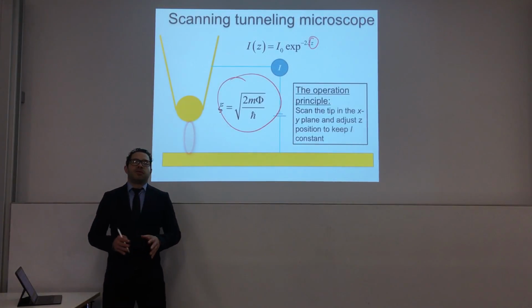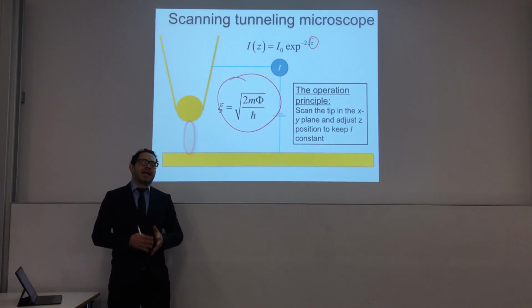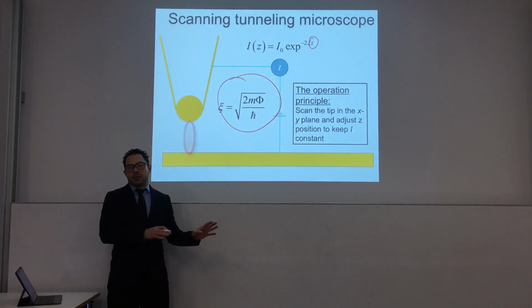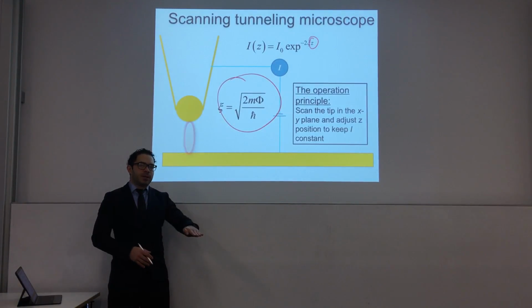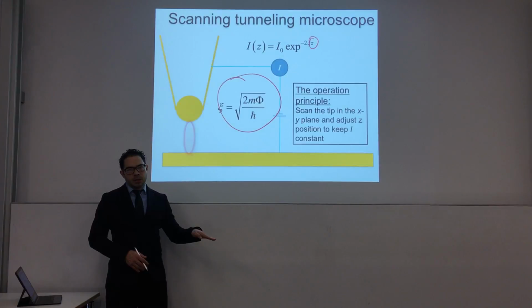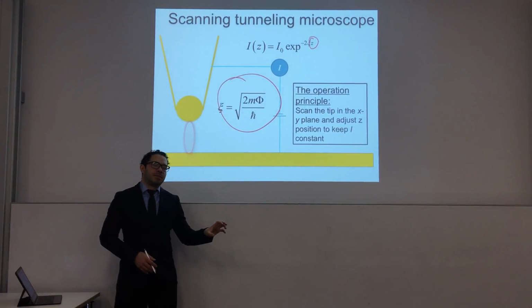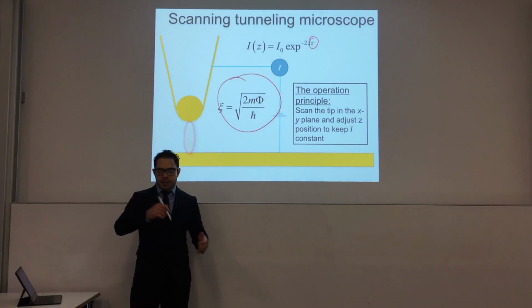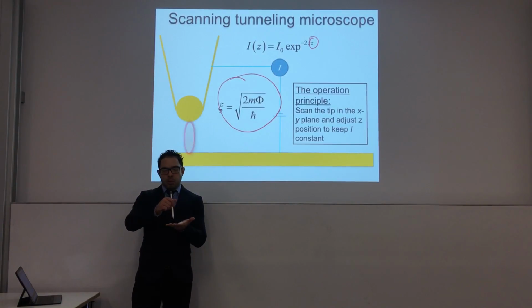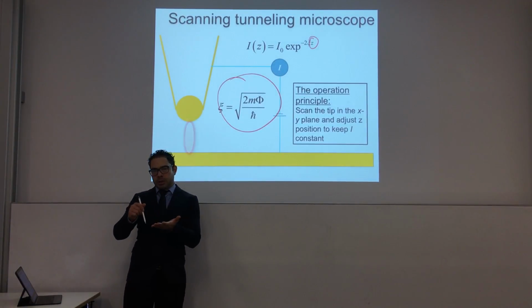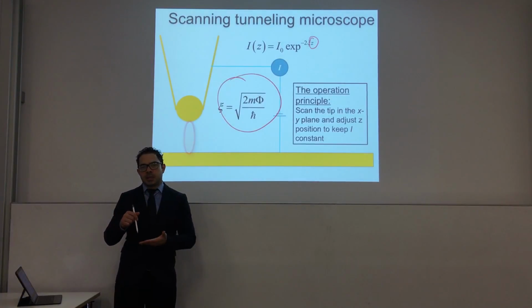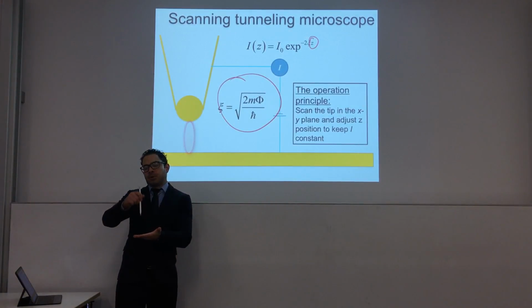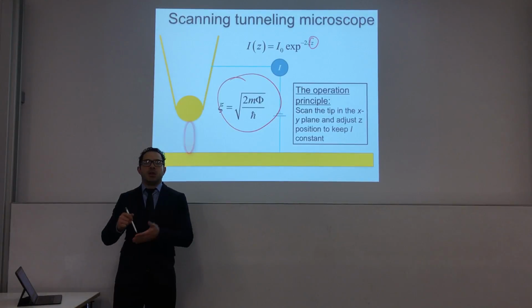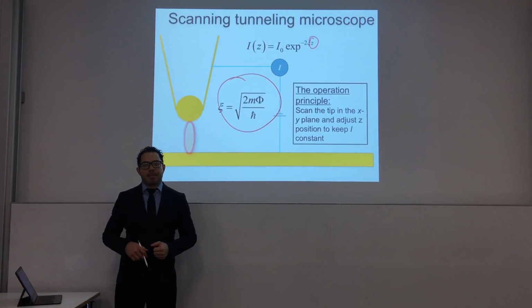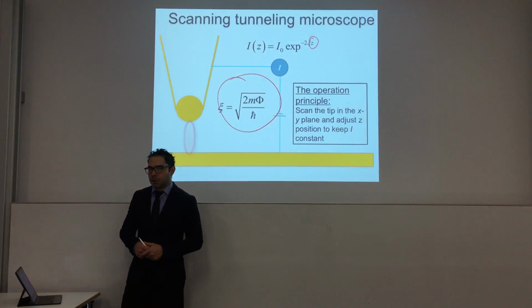What you do is define a given operation or set point current. So you tell the system: move the tip-sample distance in order to keep this tip-sample current constant. You will have a point in your sample surface, you will move pixel by pixel to another point, and if the system detects a change in current, it will adapt or tune the tip-sample distance in order to come back to the preset or selected tip-sample current.